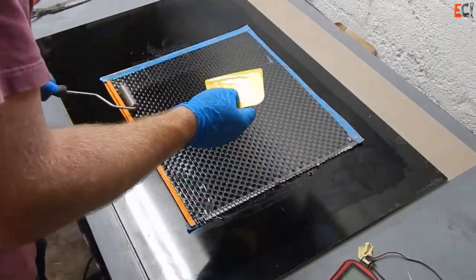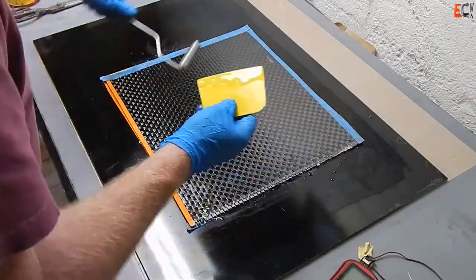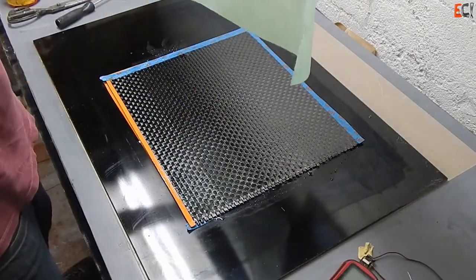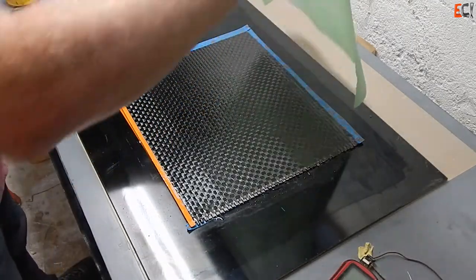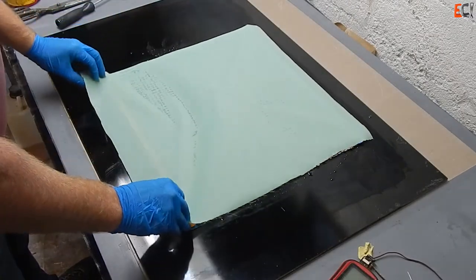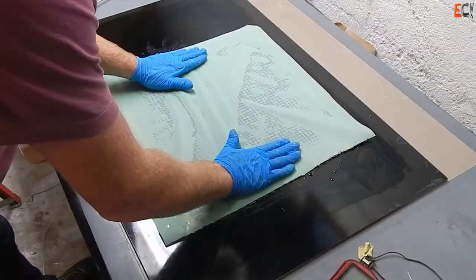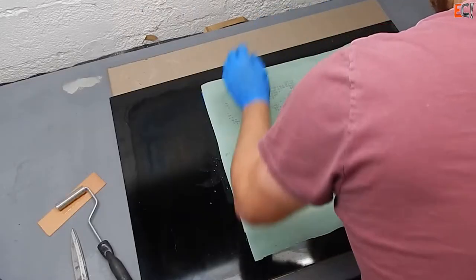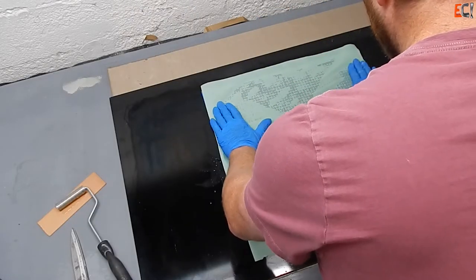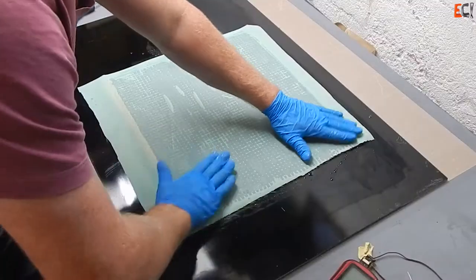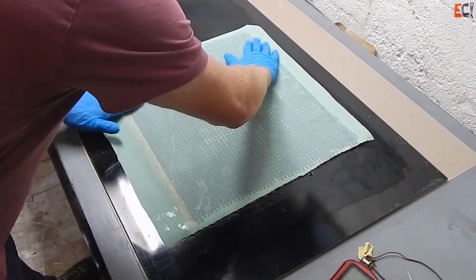So as usual I'm doing lots of rolling, rolling is relatively important especially on the bottom skin. And the peel ply here is a silicone coated nylon, silicone coated nylon peel ply made by Airtech. It has a finer weave than the uncoated general purpose nylon peel ply. Sometimes it has the red stripes that I've used in a lot of other samples.